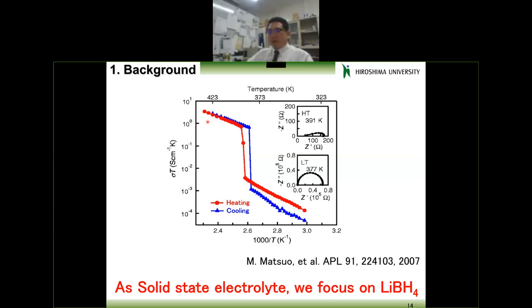Lithium borohydride, as I already mentioned, is quite a famous material in the hydrogen storage field because it has a quite high hydrogen content. Usually, a normal hydrogen storage alloy shows 1 or 2 weight percent, a weight ratio of 1 to 100. It's quite a heavy storage material. In the case of magnesium, about 7 weight percent hydrogen capacity, but in the case of lithium borohydride, more than 15 weight percent hydrogen capacity is realized. So many people focus on lithium borohydride. But in 2007, this Japanese group focused on this material as a solid electrolyte.